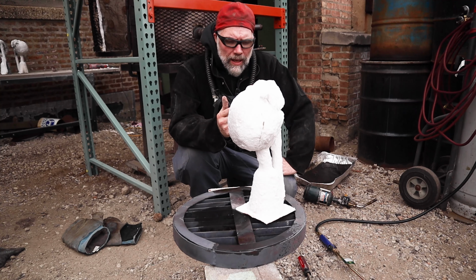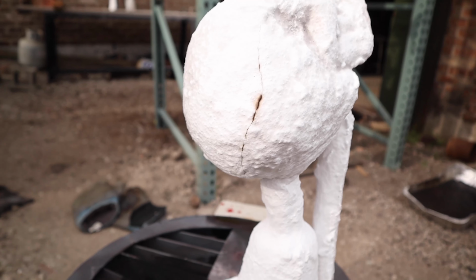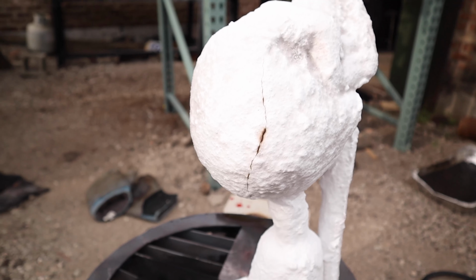I was able to go at it a little bit more controlled, going around the cup, the gate, and the vent, getting those areas out. In the end, I was probably a little bit too aggressive, by evidence of the crack that formed on the outside. But it's super manageable.